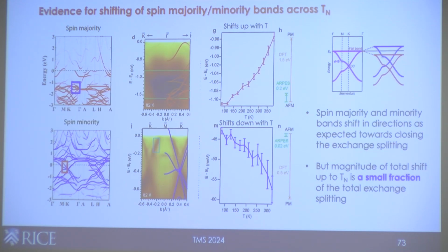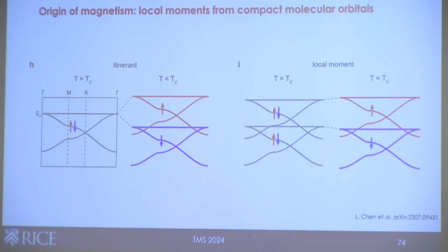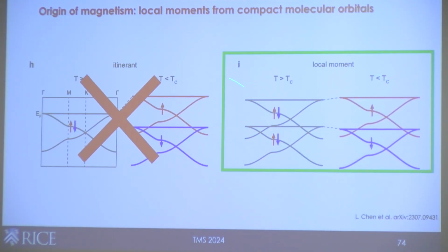So immediately, this tells us that if you compare these two pictures, it's not compatible with the itinerant ferromagnetic order, but it's much closer to the local moment picture than the itinerant picture. So this is something we have learned from iron tin.